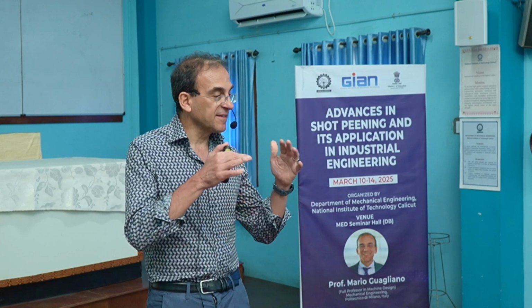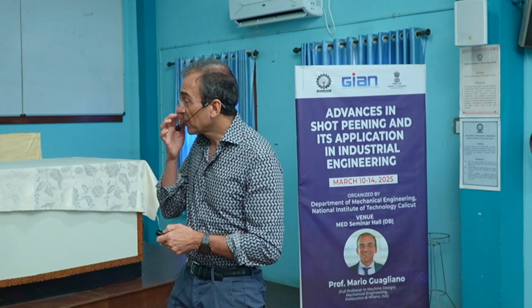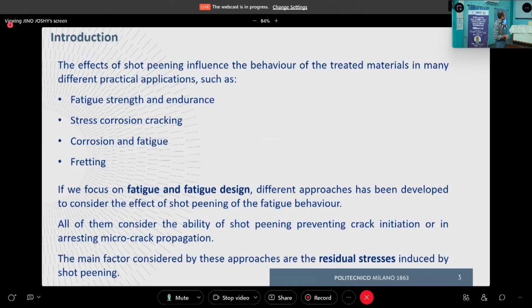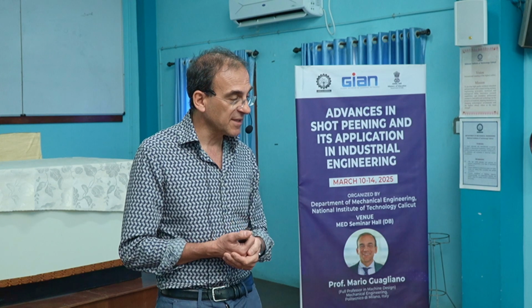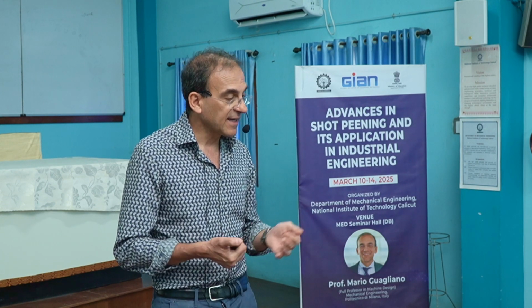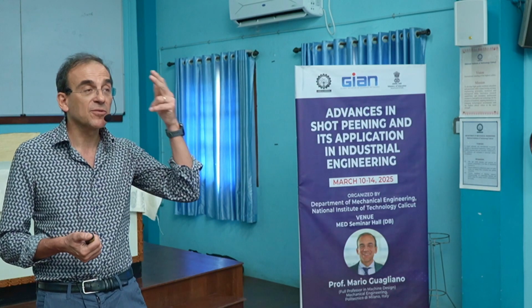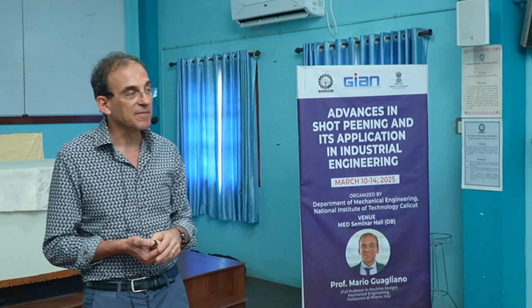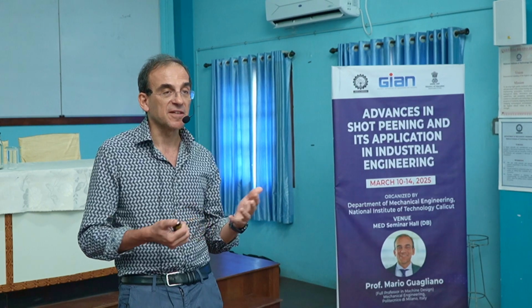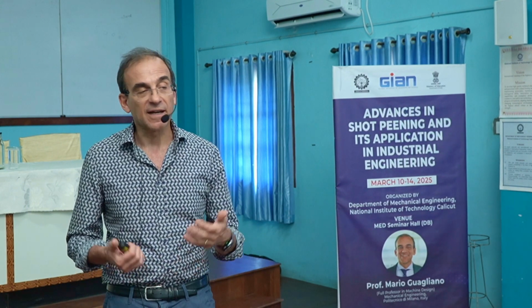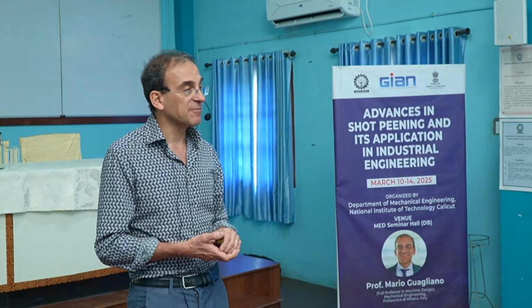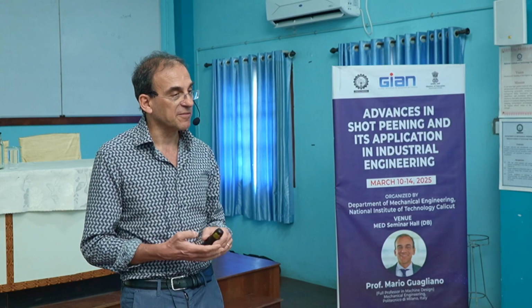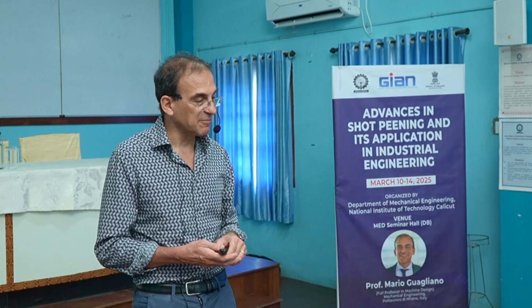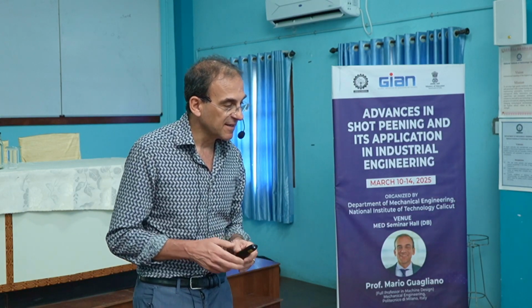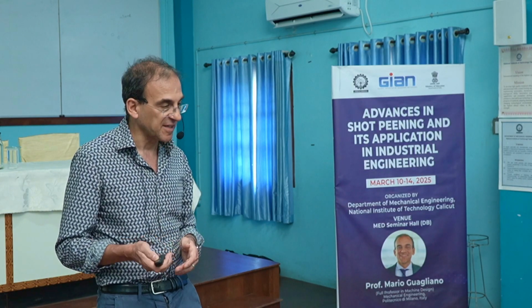Indeed, the fatigue design methods that consider shot peening sometimes consider the ability of shot peening itself to prevent crack initiation, sometimes also the possibility to arrest microcrack propagation. And it's also true that among the three effects due to shot peening, the one most widely used and considered in these different fatigue design approaches is the residual stresses. In some approaches there is also a contribution of surface work hardening, and sometimes roughness, but the main effect is residual stresses.